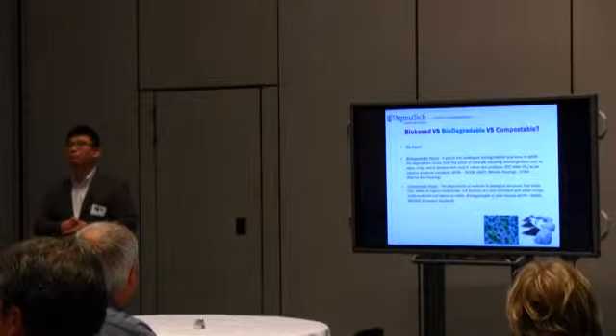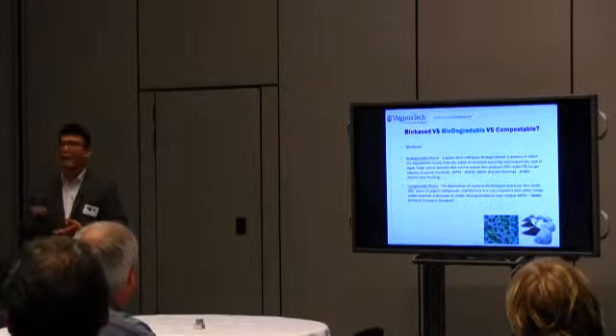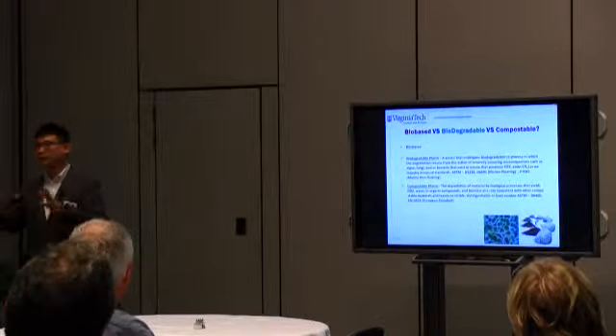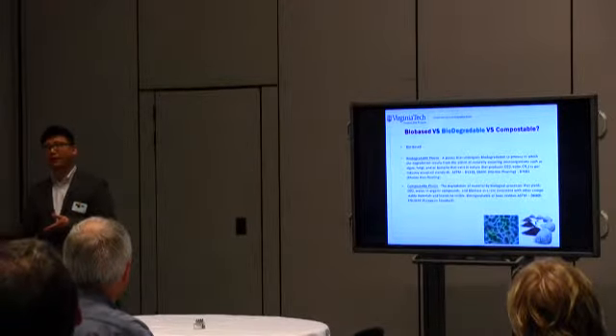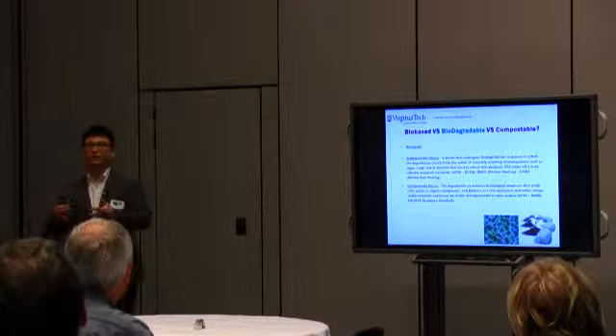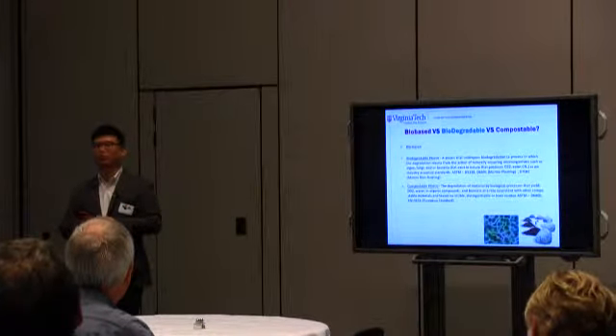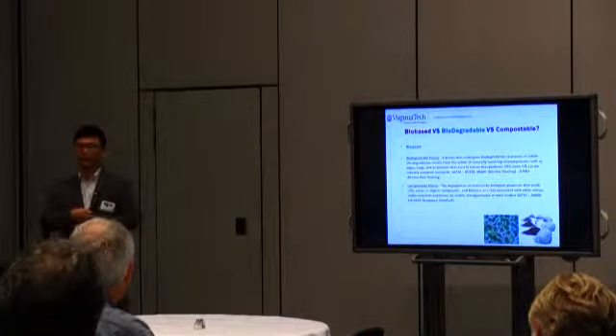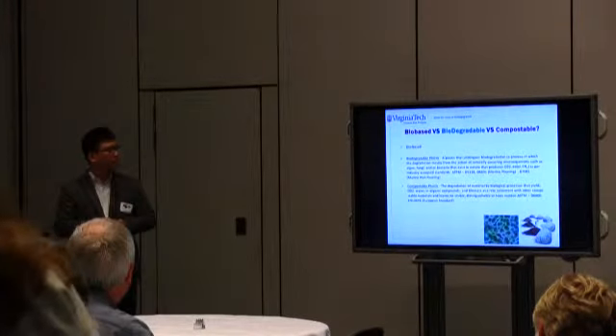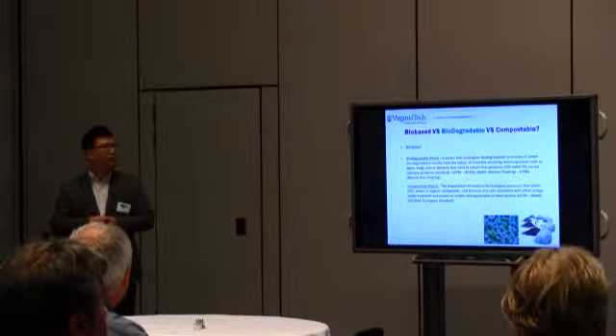The criteria is permeability, especially water vapor permeability, which is really bad. Because of that, it is not used for liquid products. For example, Coca-Cola can't be stored in a biodegradable polymer. The most common biodegradable polymer is polylactic acid made by NatureWorks. Actually, I worked with NatureWorks for 3 years on my project. I tried to increase their properties, but I found the technology was really expensive. Because of that, alternative materials, bio-based polymers such as bio-PE and bio-PET, were introduced. So again, it's case by case.